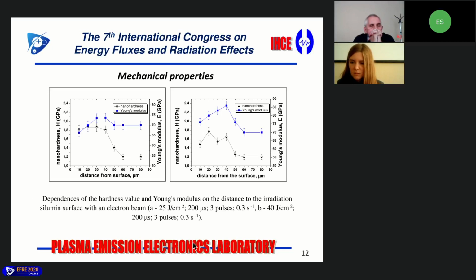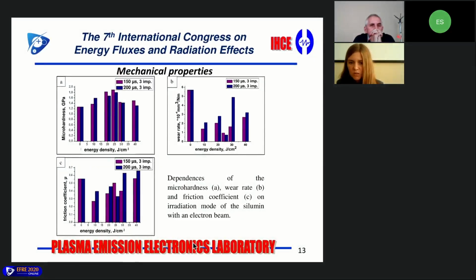Mechanical and tribological tests were performed. It is shown that in the best case, the microhardness of the surface layer, 45 micrometers thick, increases 1.4 times relative to the initial state, wear resistance increased by nearly 8 times, and the friction coefficient decreased by nearly 2 times.